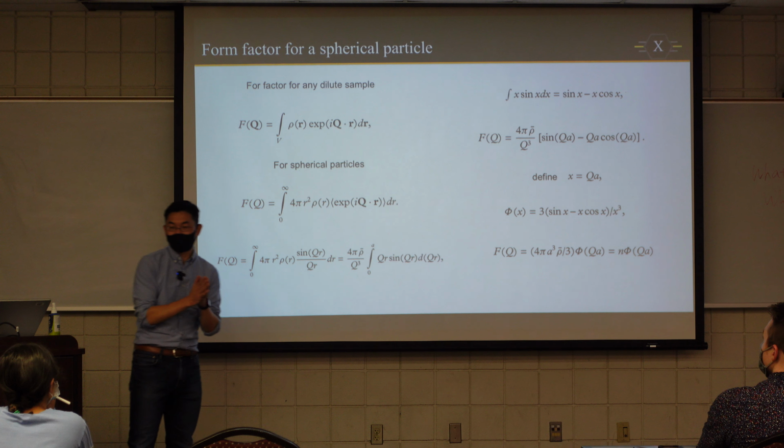It starts from the top, and it actually crosses the 0. There's a part of that where the interference of the electrons will give you a different pattern, which gives you negative phi x. And that just means there's a negative phase. And don't worry about phase, because the X-ray detector measures intensity. And intensity is just the amplitude squared, okay? So if we take a square of all the y, while maintaining all the x the same, we would come into this particular equation or plot.